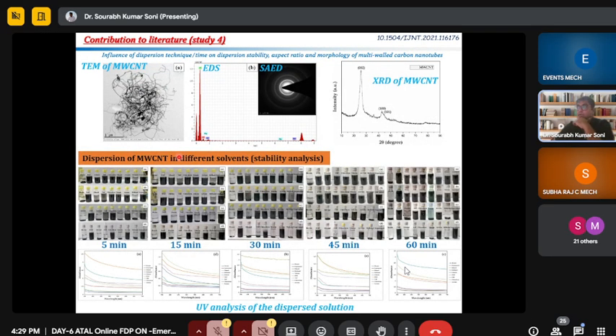In another research, I performed the dispersion of MWCNT for different durations, and then stability analysis. For stability analysis, I did the dispersion for 5 minutes, 15, 30, 45, and 60 minutes, and observed with photographic images. I even performed 30 days also, to see what is going on after 30 days. So you can do this kind of investigation also.